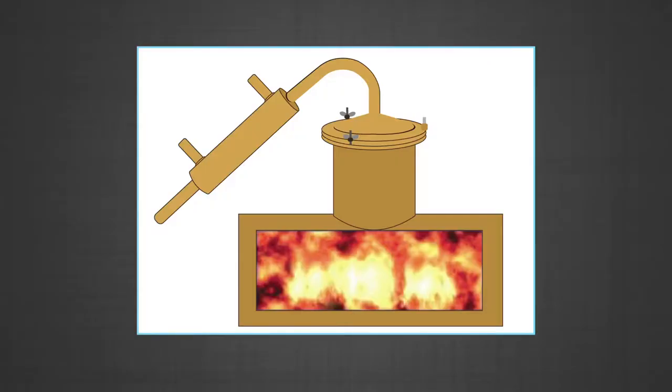First of all, distillation. You have studied about distillation as a simple technique for separation of a mixture of two or more miscible liquids. Similarly, this method is very useful for metals with low boiling point, that is metals like zinc, cadmium and mercury, which are easily volatile. The impure metal is heated in absence of air in a retort. The vapors are condensed and collected in a receiver, and the non-volatile impurities are left behind in the retort.